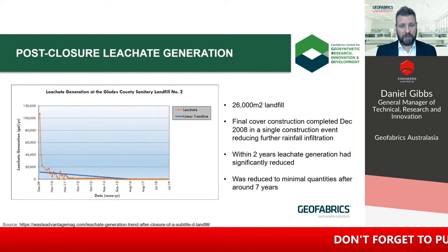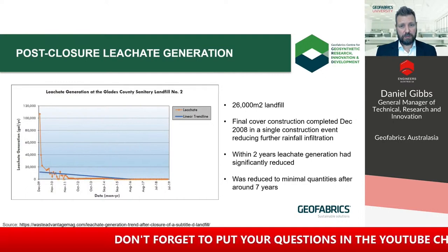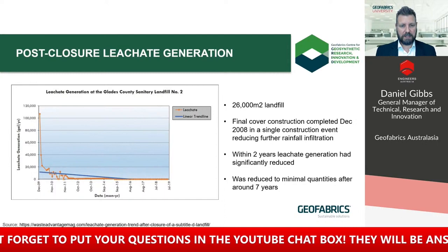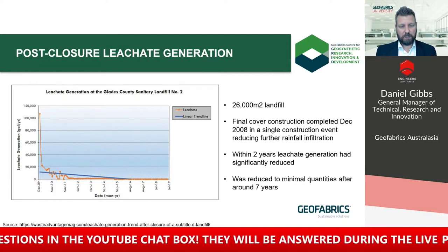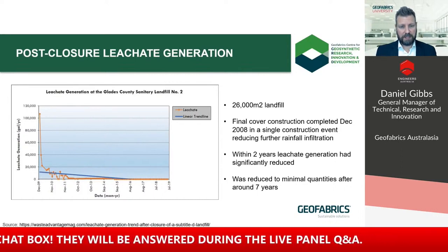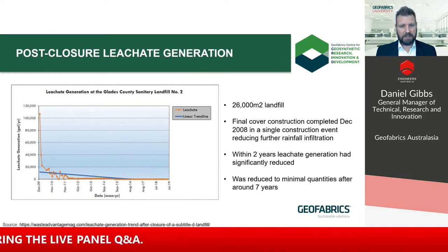The good news for landfill operators from a leachate collection and treatment point of view is that leachate generation has been shown to slow dramatically post-closure. And in this specific example of a landfill in Glades County, Florida, in the US, leachate generation dropped significantly within 2 years post-closure and then fell to virtually nothing after just 7 years. Obviously, this may not be the case for all landfills, but it certainly gives us some general insight into how long leachate may need to be managed post-closure.